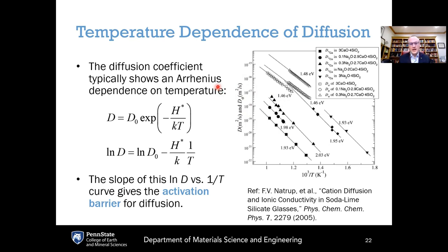So the equation for that is that the diffusion coefficient here, D, is equal to some prefactor here, D0, times the exponential of minus some activation enthalpy here, H star divided by kT. And you can see if we take the natural logarithm of both sides of this equation, we have the natural logarithm of the diffusion coefficient D on the left-hand side equals the natural log of this prefactor D0. And then since this is the product of two terms, the logarithm gives us the addition. The natural log cancels out with the exponential. And we've got minus the argument, minus H star over k times the reciprocal temperature, 1 over T.